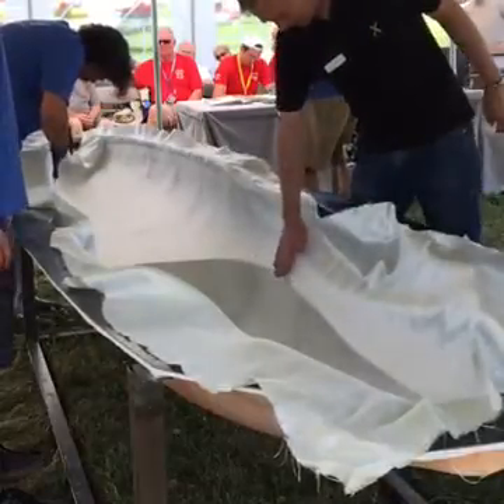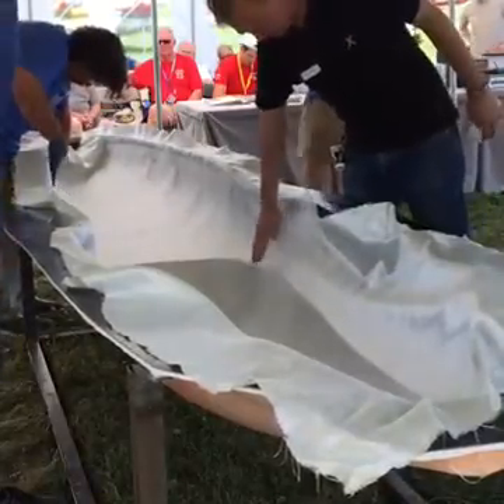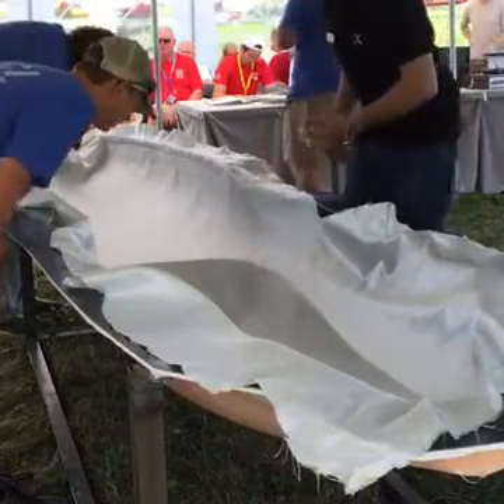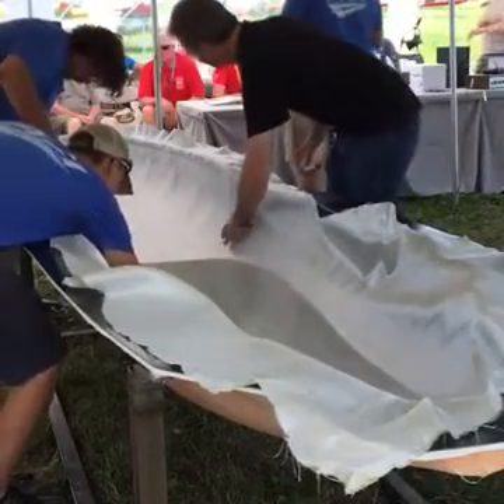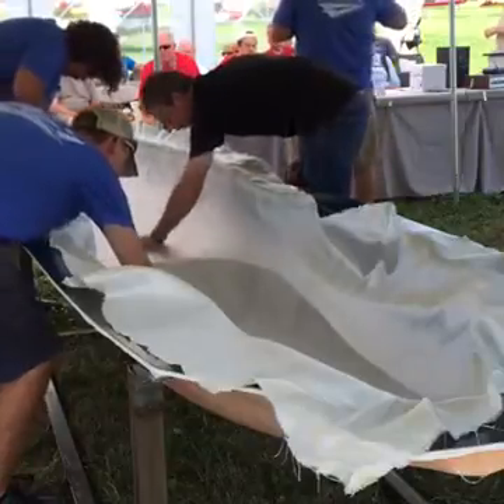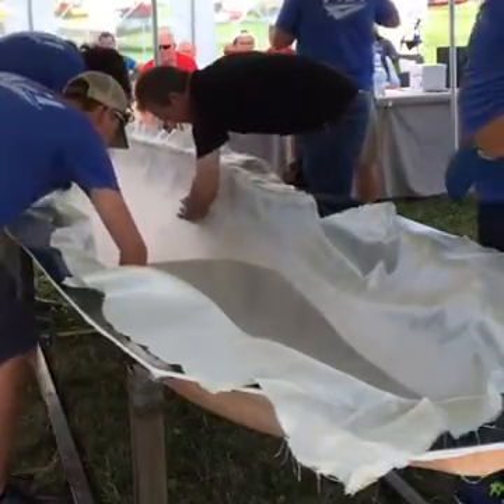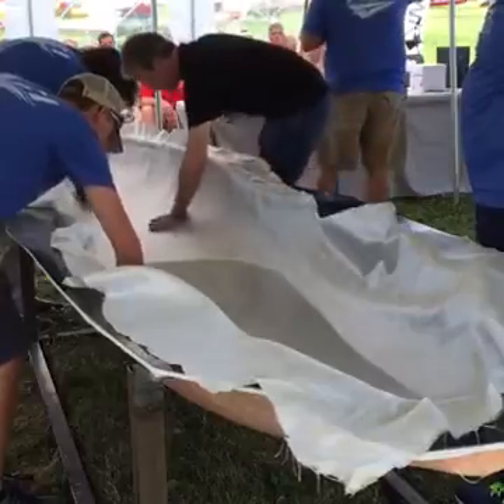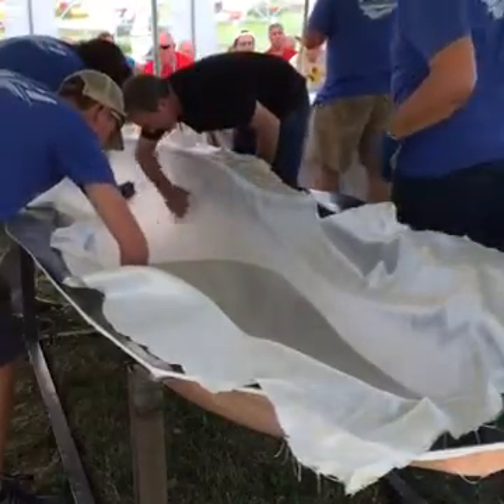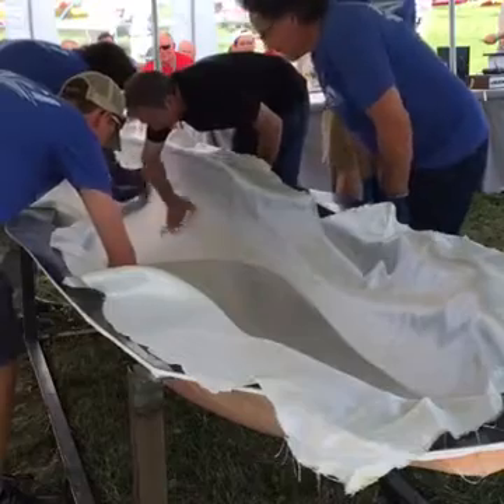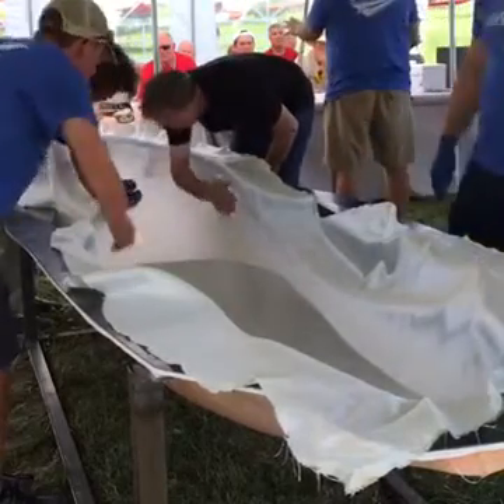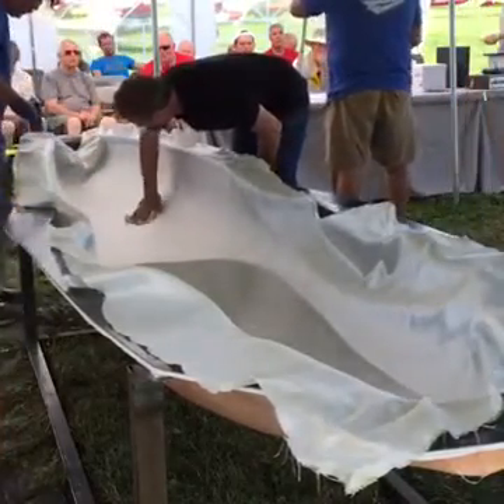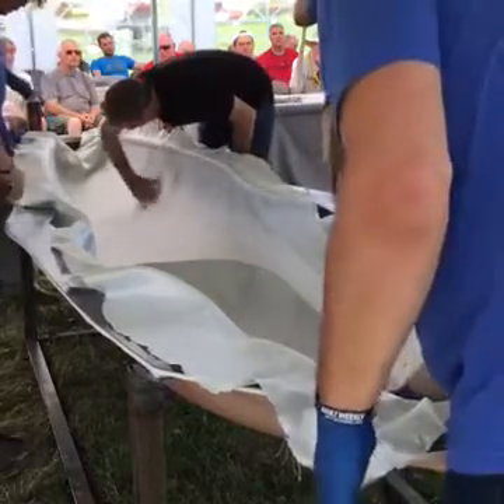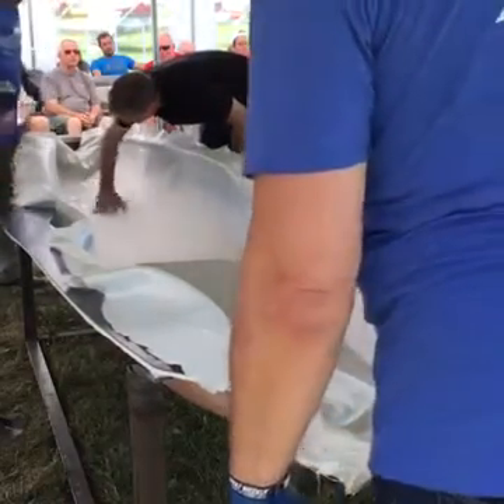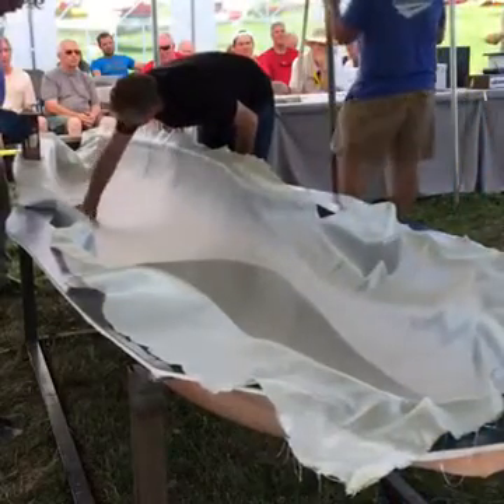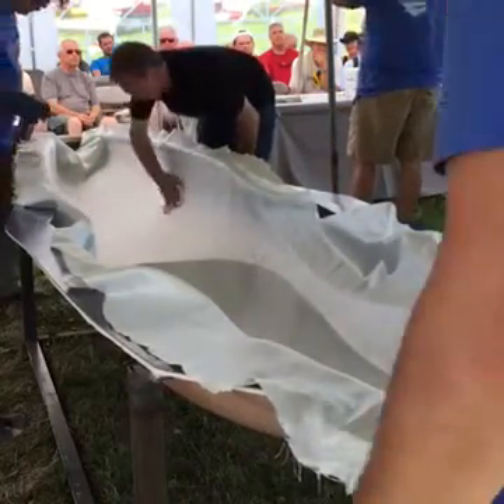Okay. So to answer Russ's questions, basically you've got about a 45-minute gel time with this resin. The way it's set up today would be about 60 minutes. This urethane acrylate cures a little bit differently than other resins do. What you're going to see is a plateau. It's going to gel, and when you touch it, it's at the gel point. If you were to take a slug of it, say 100 grams, when you go to touch it, it's going to feel like jelly, and then it'll get somewhat soft. And you think, okay, that's not cured. No, it's not. It goes to a 2-phase cure.